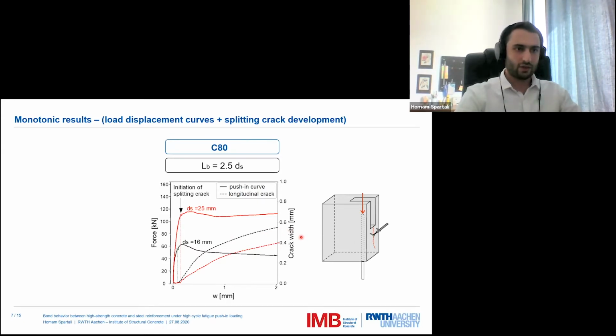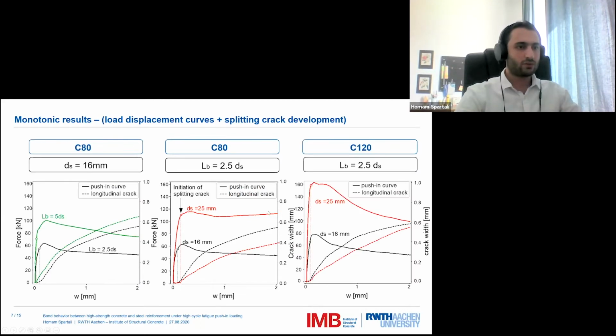Maybe I forgot to mention that the axis that we added here is the crack width, which allows us to compare how the crack width is developing with the increased slip. Now, this behavior was also observed in the other cases with the different bond, and here with the different concrete, C120, we see always this start of the crack and then reaching the top and then the deterioration with the further increase of the splitting crack.